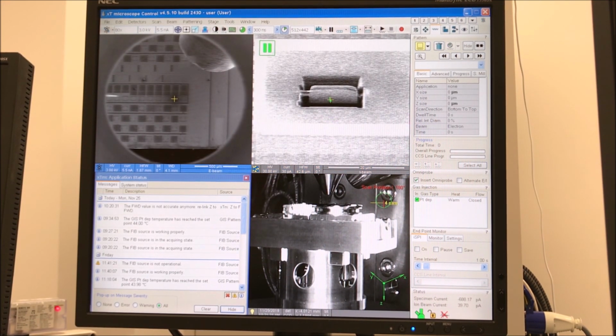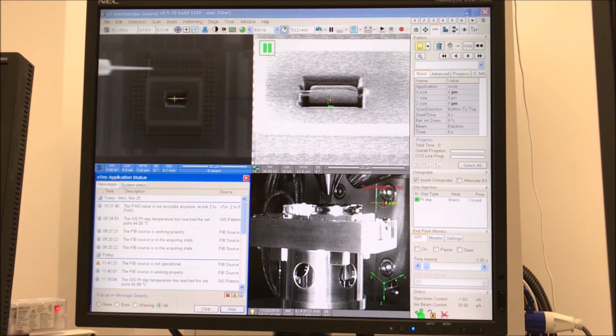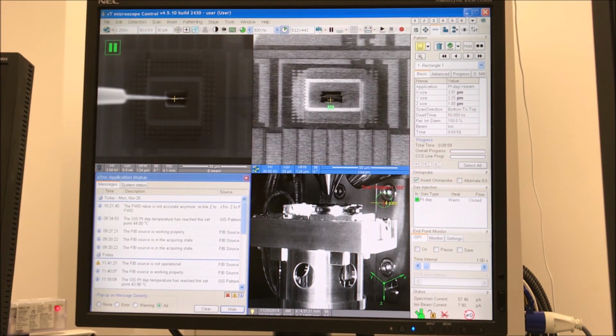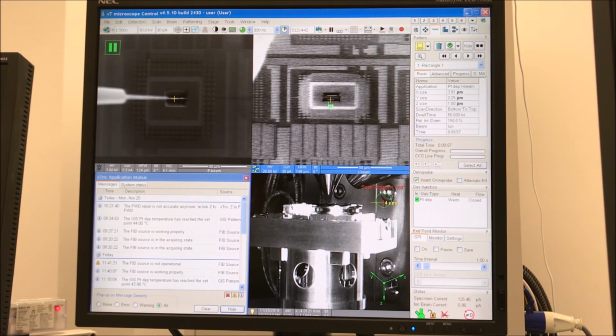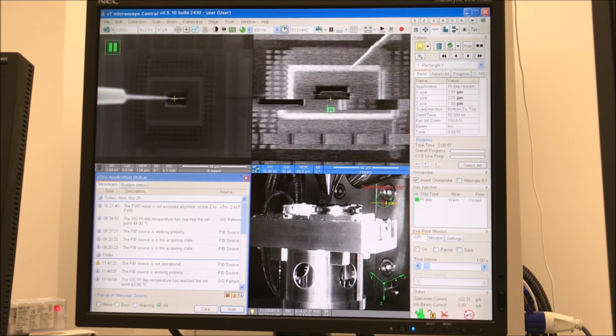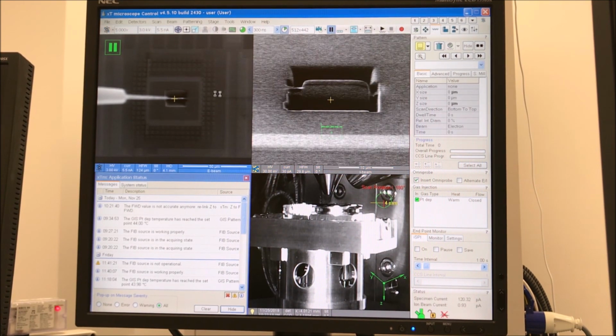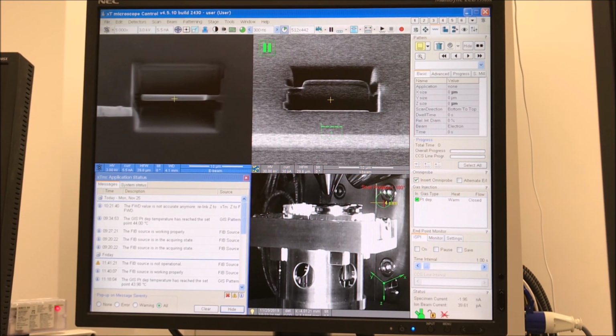I inserted my platinum and my omniprobe, and now I'm going to approach the omniprobe to the lamella. So it's coming in from the left side of the electron beam image, and because of the scan rotation set to 180 for the ion beam, it's actually going to come in from the right side of the ion beam image. And so now I have to move the omniprobe down, and this is where the dual beam capability of the FIB is important, because otherwise you really wouldn't be able to position the omniprobe tip.